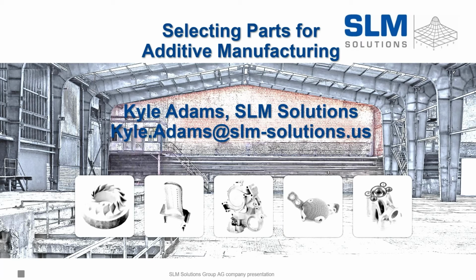That's a very good question, and right now there's no solid answer. Because of the metal powder process and how each geometry is different, essentially we need to go through qualification processes, and I assure you there are parts flying right now, so it is being done, but it's a very extensive process where the machine needs to be qualified, the process needs to be qualified, the material itself needs to be qualified, sample parts need to be made, tested, testing samples per build need to be produced for each part. Powder lot traceability all needs to be handled.